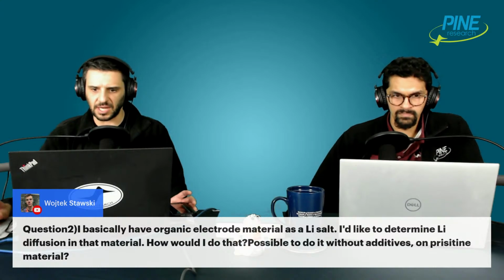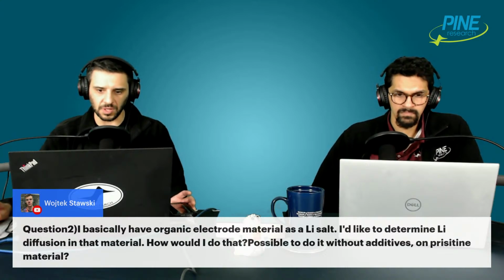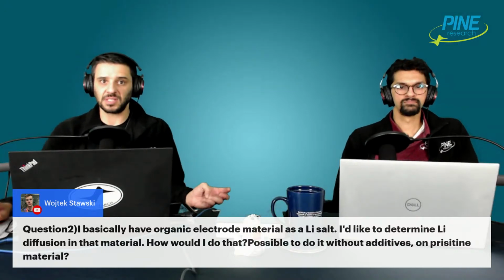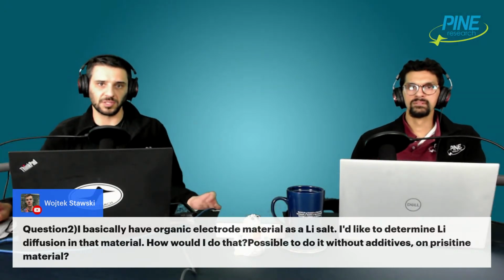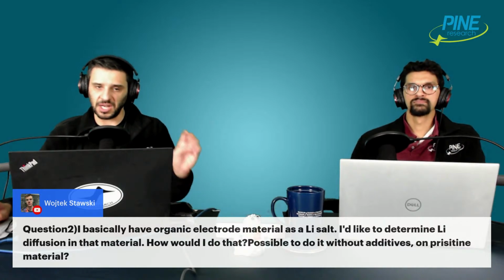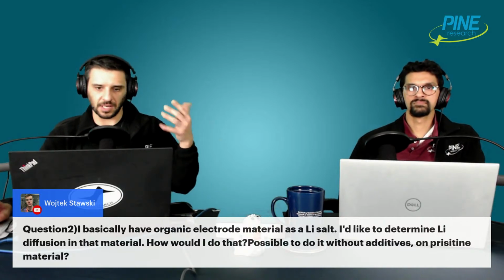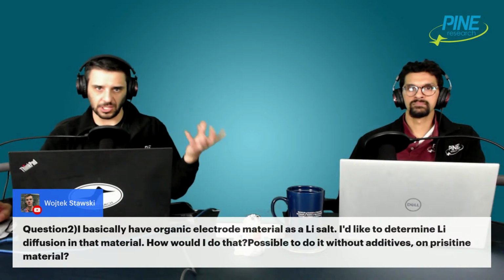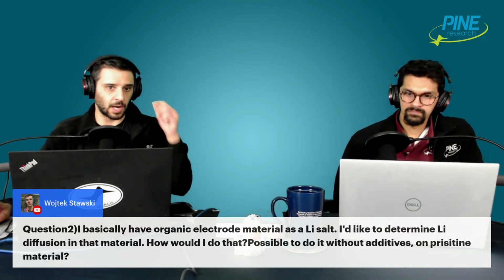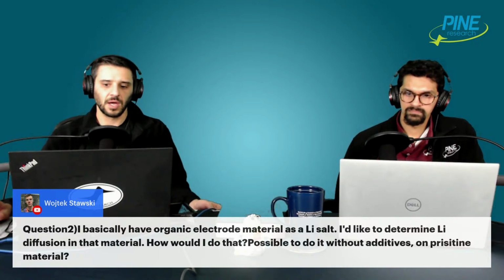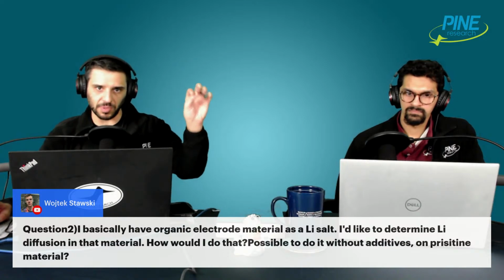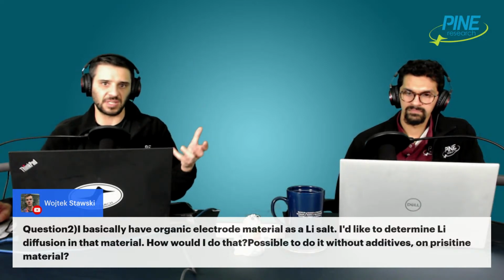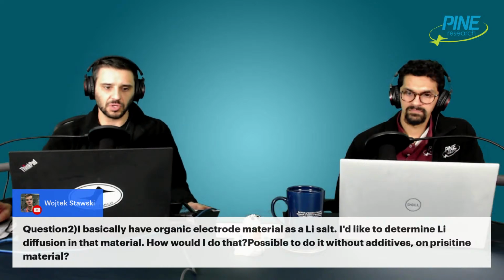It's somewhat related to your second question here, and the second part of your first question, like how it's determined. I'll go through this with the Warburg. So there are different methods for measuring the diffusion coefficient. There's one called the current pulse relaxation technique, which is not an EIS technique. It's like chronoamperometry or chronopotentiometry. PITT and GITT have ways of measuring the diffusion coefficient, mostly through a relaxation, an open circuit. You can correlate the decay of the potential essentially with diffusion.